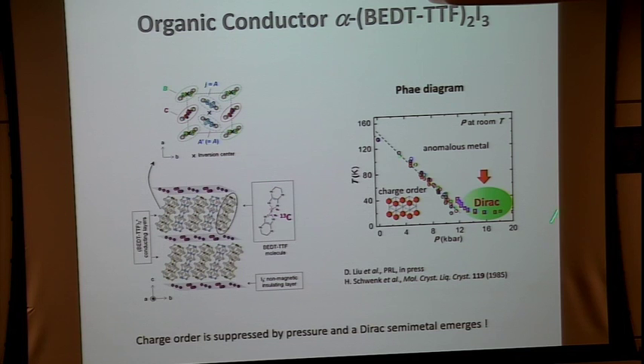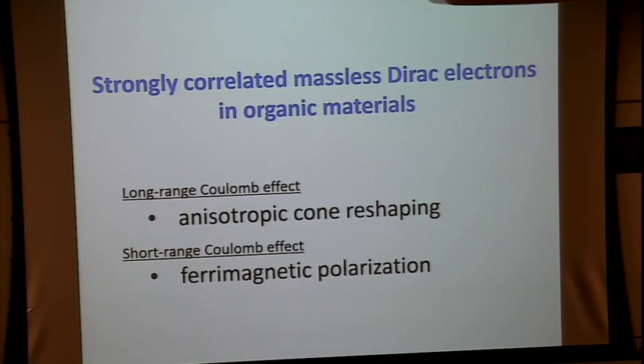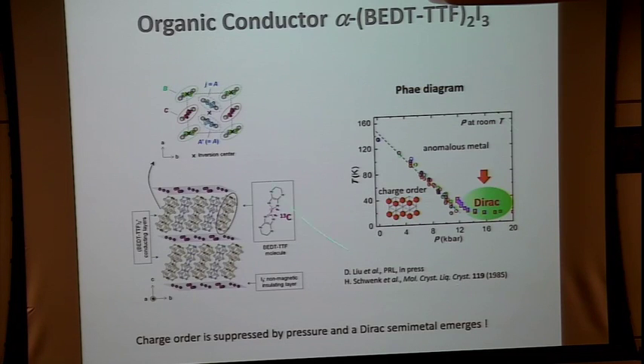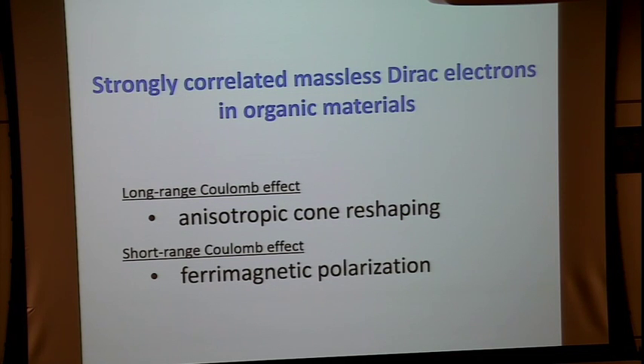And this is a phase diagram. At ambient pressure, this material shows a charge order at 135 kelvins, and under pressure, this charge order temperature decreases. And then above 12 kilobar, the Dirac fermion phase appears. Okay, I'd like to show you the interaction effects. This phase diagram suggests the Dirac state is strongly correlated because the charge ordered state is neighboring. So I think in this organic material, you have strongly correlated massless Dirac electrons.